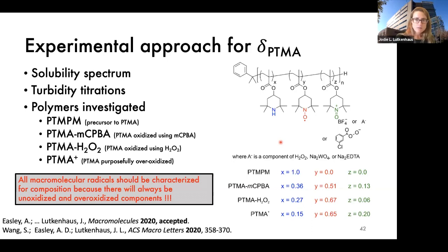Now, one of the things I want to emphasize to this community is that when we make a radical polymer, it doesn't always look like the ChemDraw that you want it to be. You actually have some fraction of the oxoammonium cation and this amine group present in your polymer. And if you really want to understand your material, you need to characterize it and quantify how much of this X, Y, and Z you have. And depending on the oxidation method, you will have different ratios of these 3 groups. That's something we characterized using XPS, and I would encourage you to do that as well. So for solubility studies, we need to know this because we're trying to eventually report solubility parameters for these groups.